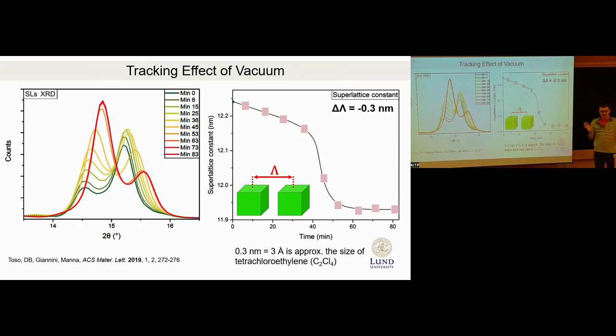So what happens is that you remove the trapped solvent from your film, nanocrystals move closer, that changes interparticle distance, hence modifies your interference pattern, and then for each time point we can extract lambda and see that after about 80 minutes under vacuum, we contracted our superlattices by about 0.3 nanometers, which is consistent with the approximate size of a tetrachloroethylene solvent molecule. So that was a simple interpretation of this result, but it shows what we liked about it, the power of this simple Bragg analysis.